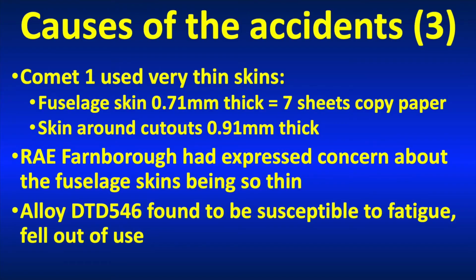So, the Comet fuselage used very thin skins. Now, 0.7 of a millimetre is 7 sheets of copy paper. That's all it is. 7 sheets of 80 gram per square metre copy paper that you'd use in your home printer. Now, the skins around the windows were a little bit thicker, but RAE at Farnborough were very concerned during the design phase about how thin these skins were. And this alloy that de Havilland used, I don't believe was used again, because it was found to be prone to fatigue. So not something that you want either.